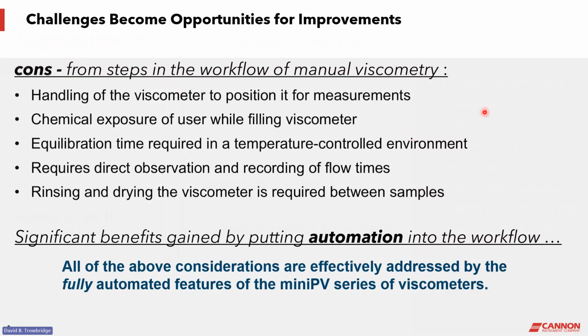So for all of these advantages, there still were cons. It's very labor intensive, and people using the manual viscometer had to manipulate the viscometer. That is, they had to be careful to handle the glass. They had to position it vertically. Vertical orientation was important to reproduce in the bath. You had to have exposure to the chemicals that are used when you're filling and washing the viscometer. You have to wait for equilibration time after you put it in the bath.